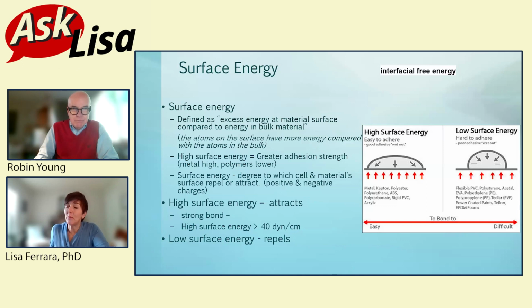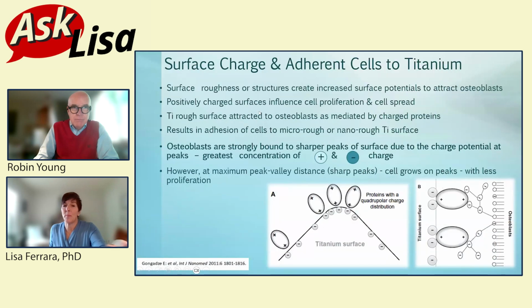Okay, so what does that mean and how are you going to know? Well, go back to the charges, excuse me. When you have a rough structure, these structures create charges at the surface and they can attract different types of cells. Again, it depends on the charges, it depends on the shape and the peak, etc. But let's use osteoblasts for obvious reasons, where positively charged surfaces will influence the cell proliferation and spread of those osteoblasts. The sharper the peak in titanium, the more dense your positive charges are, as you can see in figure A, at that peak. So you're going to get greater attraction to those osteoblasts. And where you've got maximum peak valley distances, those cells will actually grow on the peaks of that surface.